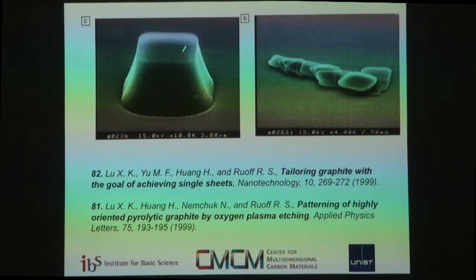So actually, one thing I want to do in the CMCM is revisit this and try to figure out why it didn't work. I think there's at least a possibility that the individual layers at the edge are somehow, from the processing, perhaps there's an ether-like linkage with the oxygen, they're somehow bound together, and they're not allowing the intercalants to go in. But we didn't really pursue that, and frankly, we weren't really funded to do this research, so I had to sort of stop it at a certain point, and then I moved from Washington University's Department of Physics to Northwestern University.